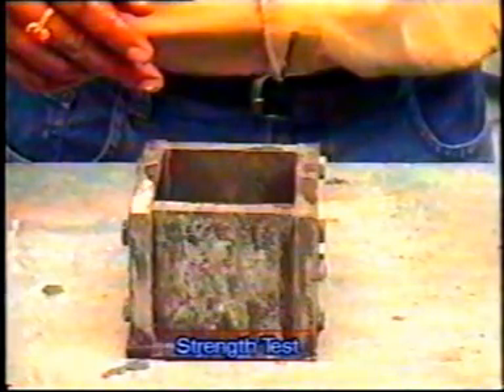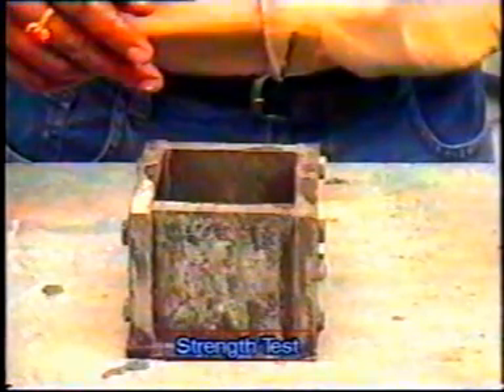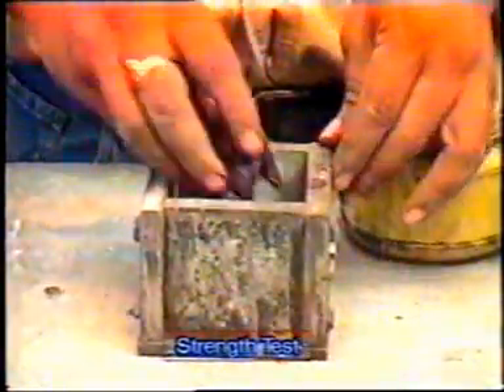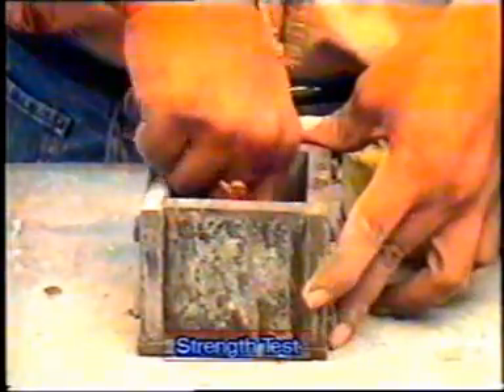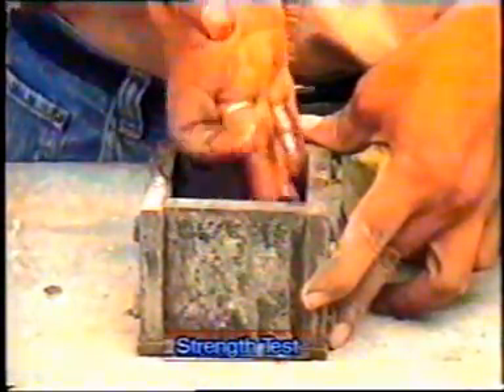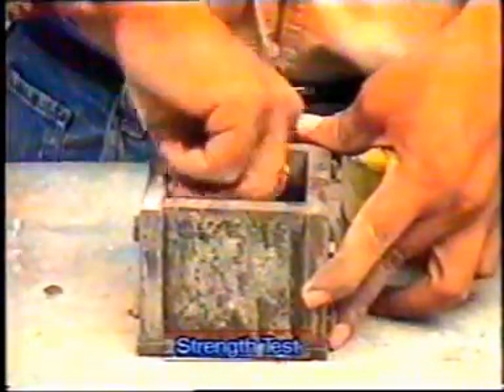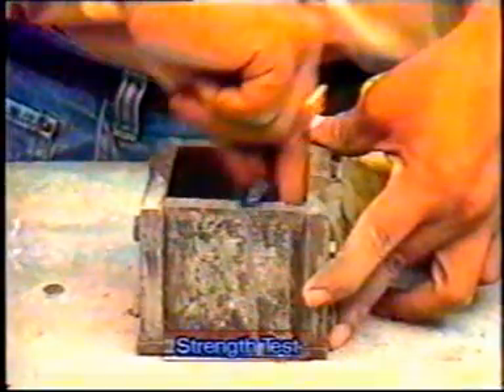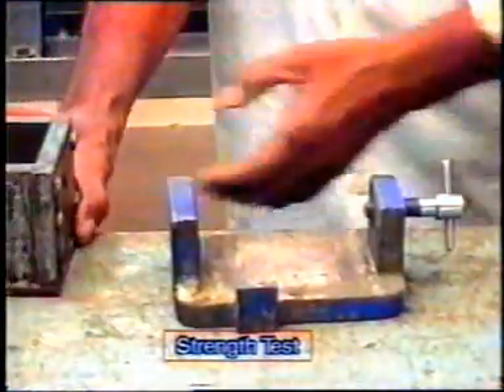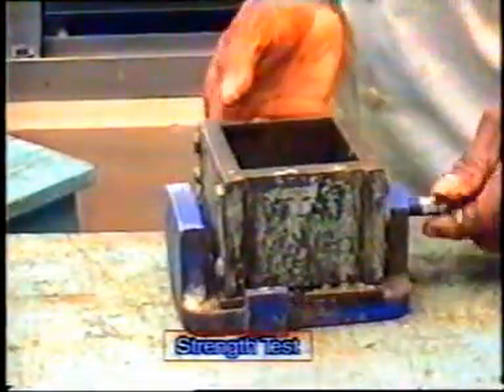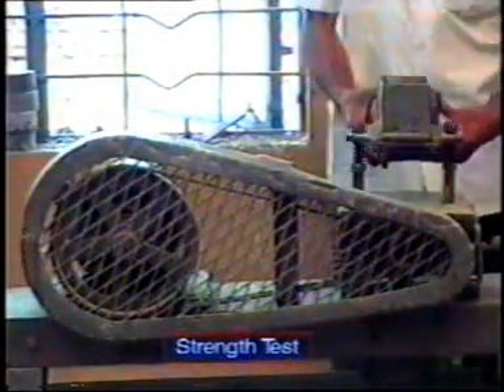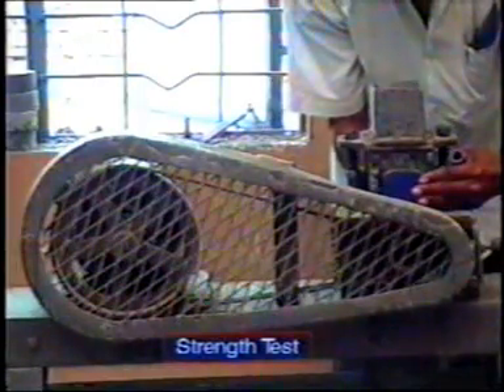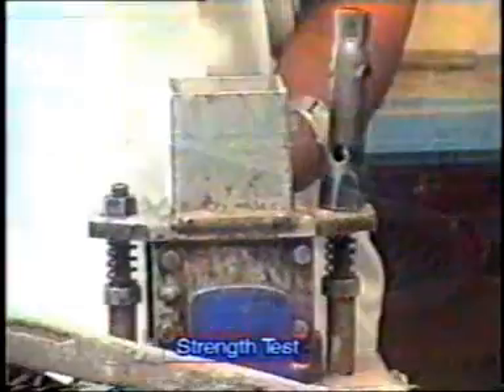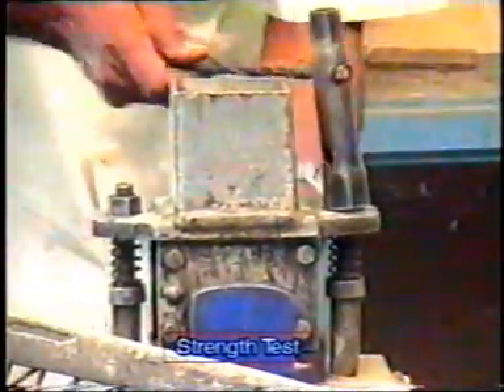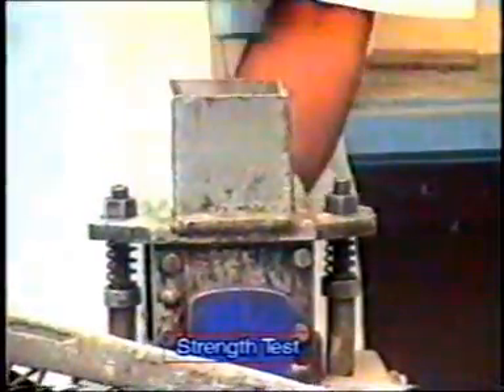Now let us see the procedure of this strength test. A thin film of petroleum jelly is applied to the contact surfaces of bottom of mold and its base to avoid water escapes during vibration. After applying the petroleum jelly, fix the mold in the vise and place the assembled mold on the table of vibration along with vise. Finally, hold it in position by means of suitable clamps on the vibration machine.